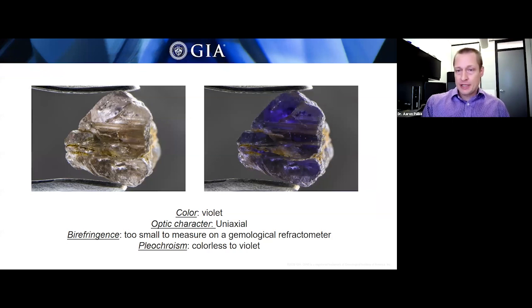One of the most striking things about johnkoivulaite, and one of its defining characteristics, is its pleochroism. This was actually a little bit of a surprise to me because the birefringence is actually very small. The difference between the refractive index in different directions in the crystal was 0.002. That was far too small for us to measure accurately on our standard gemological refractometer. We actually had to work with Tony Kampf at the Los Angeles Museum of Natural History. He has specific refractive index matched oils that he was able to use to measure the refractive index very carefully.